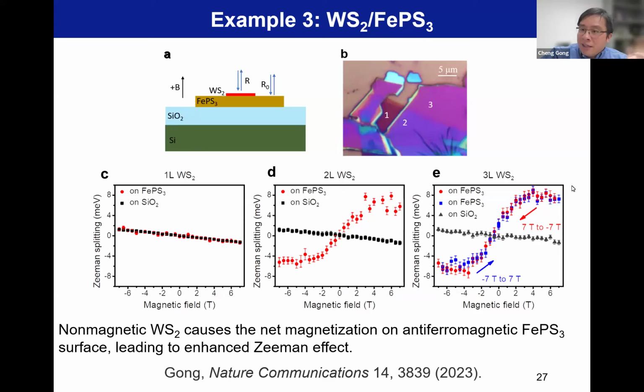But when I put two layer and three layer on iron phosphorus sulfide, you can see the slope is enhanced by an order of magnitude compared with tungsten sulfide on silicon oxide. And also there is a saturation region at about 3 tesla. So it strongly suggests there may be some net magnetization formed at the interfacial layer. So that means the tungsten sulfide converts the surface layer of iron phosphorus sulfide to kind of like a ferromagnet, creating some net magnetization. So anyhow, these three examples show interfacial effect can largely change the magnetic property.